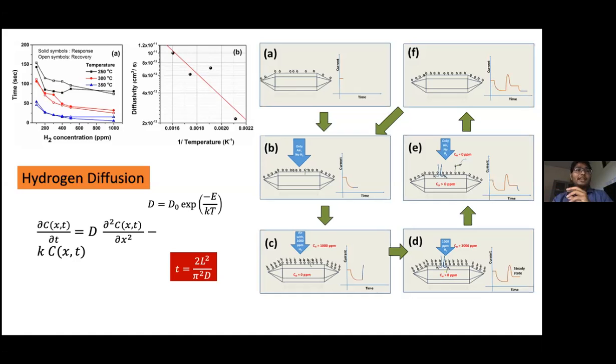Now when I put more oxygen into this particular lattice, more oxygen gets adsorbed on the surface. So where will this oxygen bind? It will bind at the surface vacant sites, the deficiencies, the defects which are present on the surface. Those are the active sites where it can readily take up. Once that takes up, some of the charges are trapped into this trap state and your current decreases. When you expose it to hydrogen, being an electron donor, it reacts with this surface adsorbed oxygen, and the current increases.